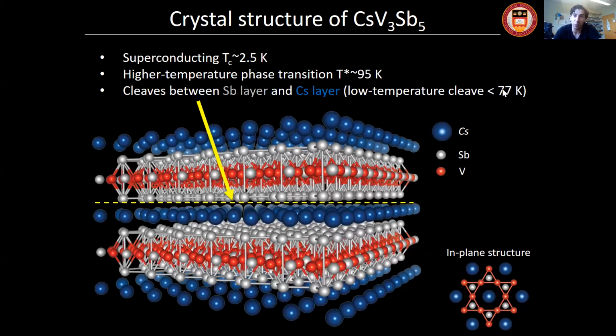And the way we do it is, for these systems, liquid nitrogen cleaving didn't necessarily work as well as we'd like. So we put them directly into the STM with the cleave bar on, so they are at about 4 Kelvin. And then we quickly take them out, cleave off the rod and put them back in within like 20 seconds or something. This is a detail I usually omit, but given the audience, I thought you might find it interesting. It's a regular UHV cleaver with nitrogen, which just gave us slightly worse cleaves.